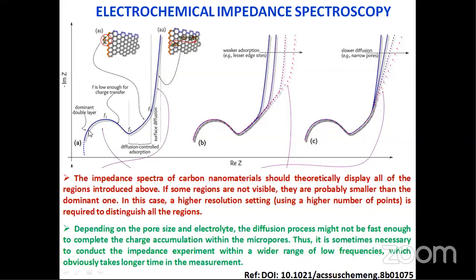To get such a typical behavior, it is mandatory to test your electrode in a wide range of frequency. If you say, for example, I will test it just from 40 Hz to 100 Hz, or from 40 to 1,000 Hz, you can't get the entire phenomena. If you test your electrode material within a wide frequency range, only then can you have all these phenomena. You see here, this is adsorption domination, and this is the charge transfer phenomena and diffusion controlled. And I have practical examples also of how it looks.